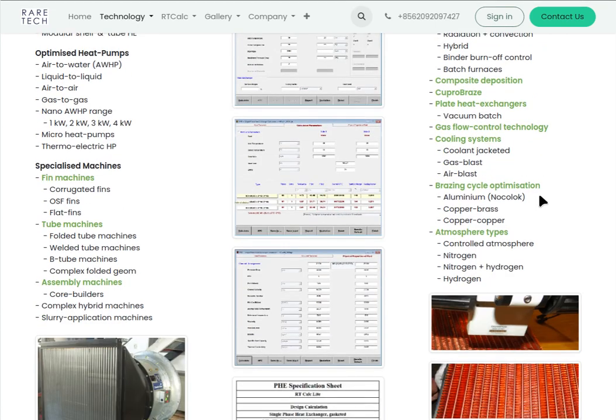Brazing cycle optimization, this is absolutely critical. So aluminium is critical because you've got a very small distance between the eutectic point at which you get the eutectic to melt and the overall softening temperature of the aluminium that you're trying to braze. Very careful, because you've got to build those cycles in a very, very careful, slow, gradual movement into the actual braze temperature. Whereas with copper and brass, we have got a very different cycle.